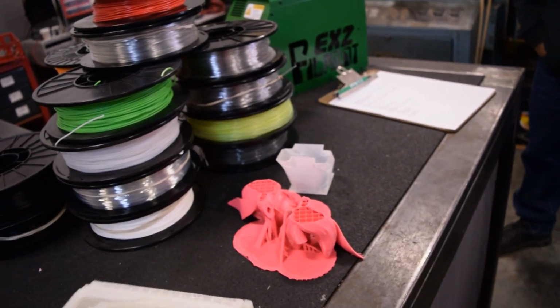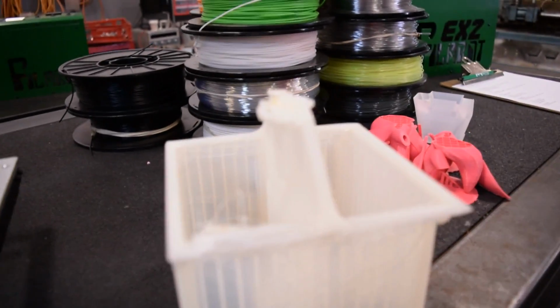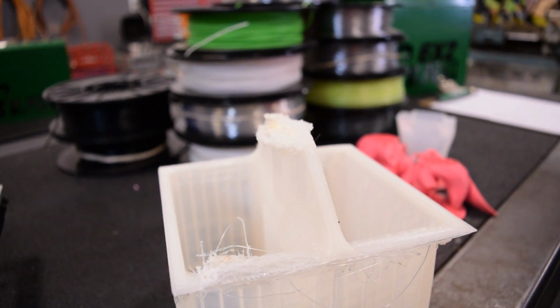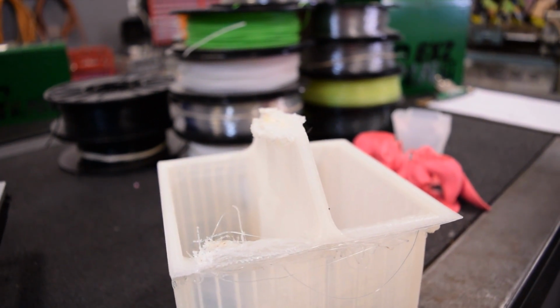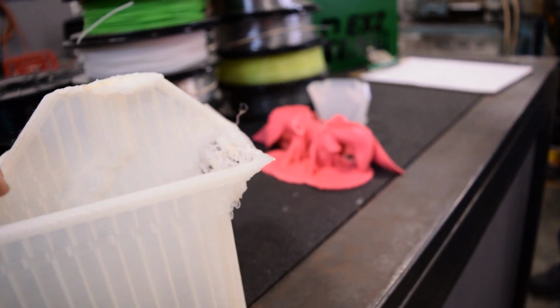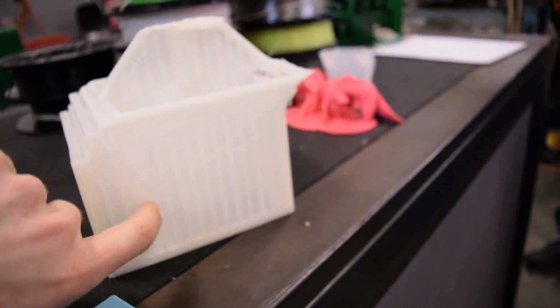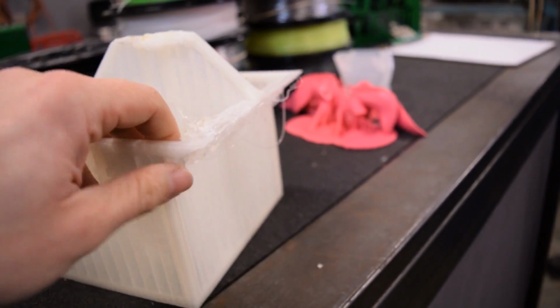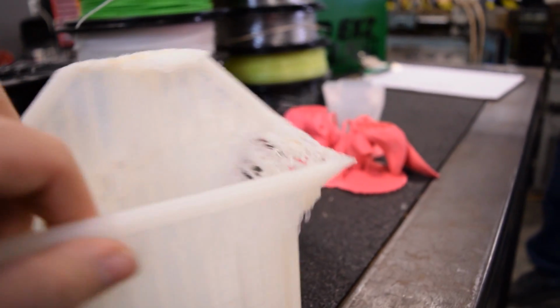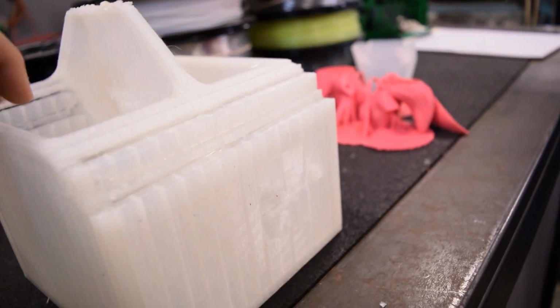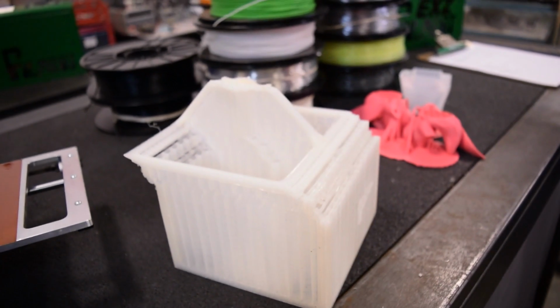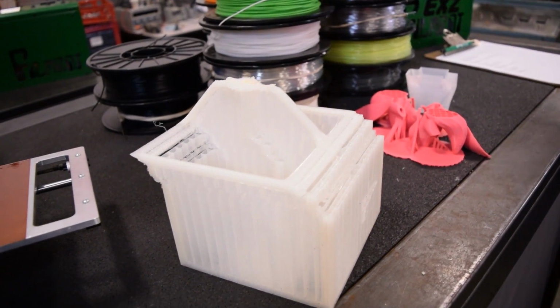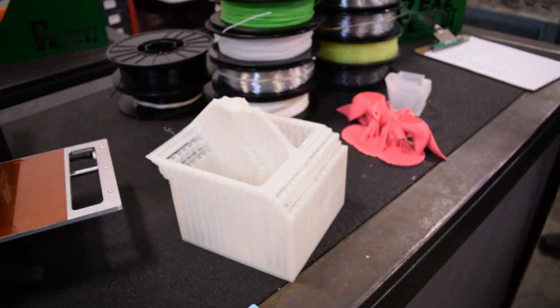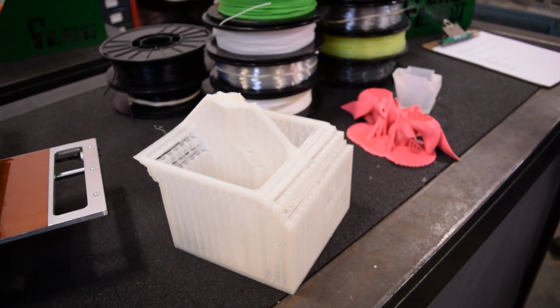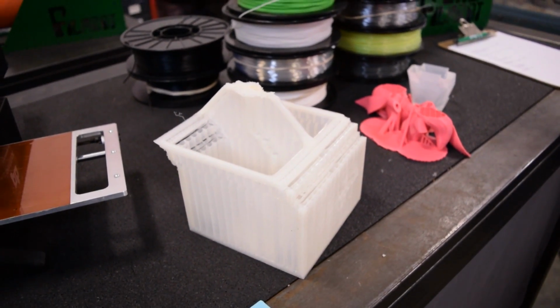Another very common issue is edge warping. So what you'll have happen is, especially on overhangs, if you don't have a lot of support material, this is like a big square frame print. This is support material, and sometimes, it looks like it happened around the support material, but it's the same issue where the polymer shrinks, and what happens is the edge of the part curls up somewhere, and this happens especially on overhangs,